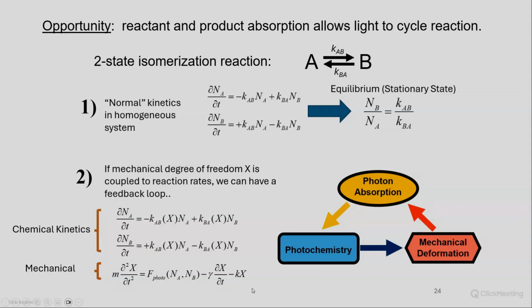So now you have a more complicated network of kinetic equations, and this gives you the opportunity to have a feedback loop between the absorption, the photochemistry that's happening in the crystal, and then the mechanical deformation. If it bends, you'll absorb less light, and so that affects the photon absorption, and so you can start to go in this circle. And what that does is it allows you to avoid that stationary one-dimensional equilibrium position that you get with normal kinetics, say in solution or a homogeneous system.